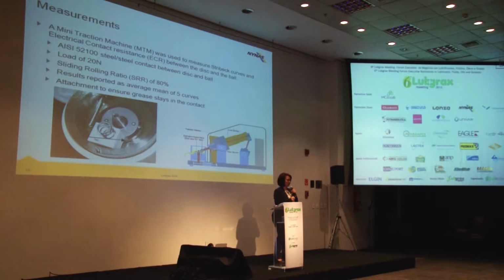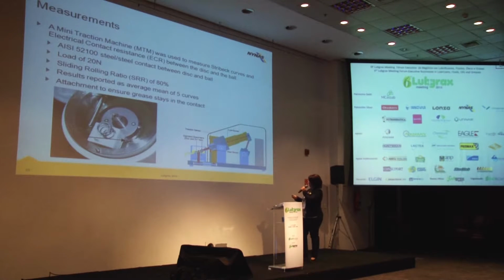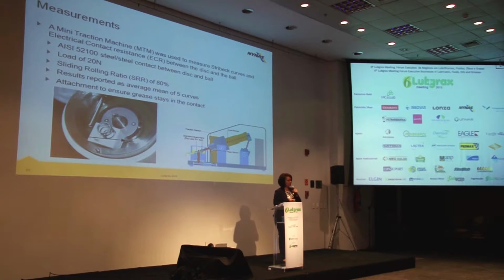So this is a ball on disc setup. You might not be able to see, but you generally have a ball here and the disc. And there's a picture there. That's the disc. Because of the mini traction machine, there is an issue about the grease in the test rig moving out of the contact zone, and then the results that you get are not accurate and not representative. So there is a plastic piece attached on top, and that was to ensure that the grease was staying in place, so you could rely on the results.